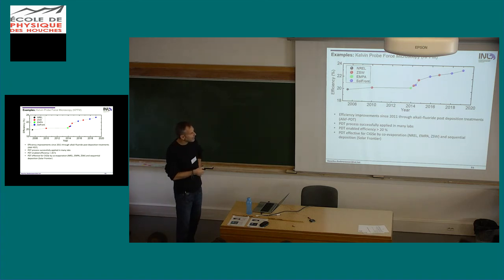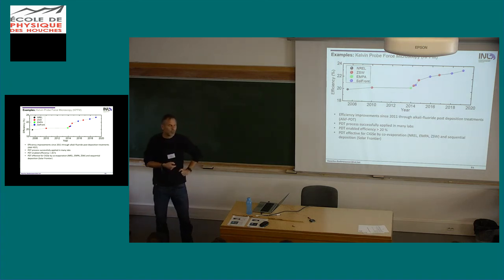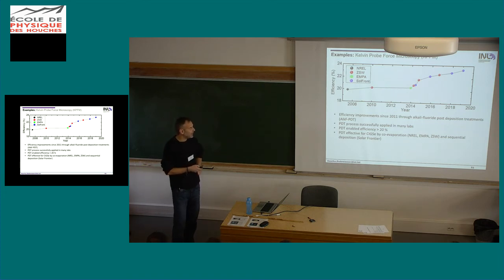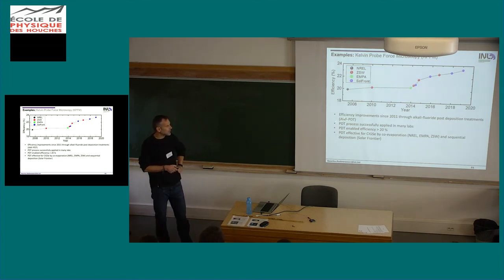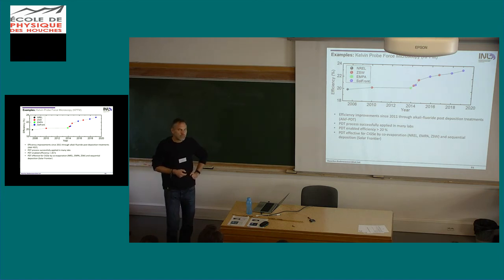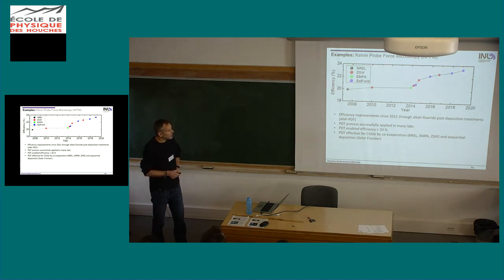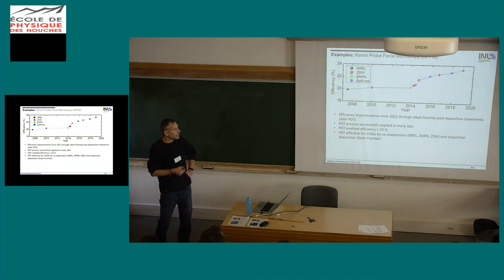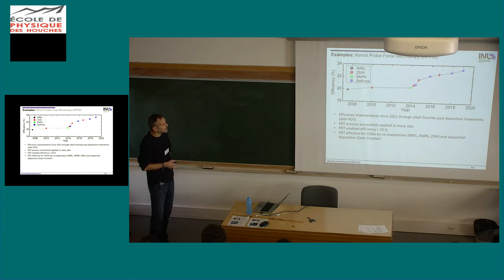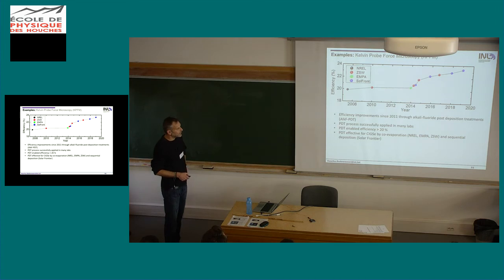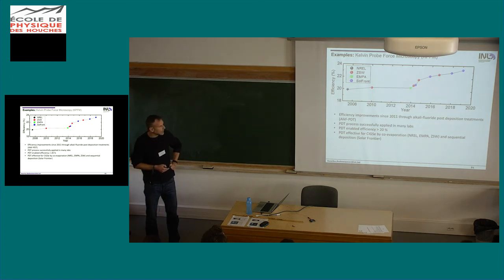So they developed the post-deposition treatments, but then EMPA and ZSW, instead of only using sodium, started using potassium and then later other alkali elements. And this post-deposition treatment was adopted fairly quickly by many different labs, and they all had success with this, and many of them eventually reached efficiencies above 20%. And this was essentially this step here in 2014, a very quick sequence of improvement in efficiency by a few percent. Now it's more than 3% efficiency increase due to this alkali treatment. And this was effective in different samples, prepared in different ways, co-evaporation and sequential deposition. We saw this a little bit yesterday already.